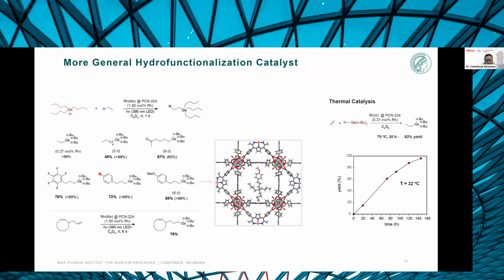What was interesting here is that we saw a real step function in terms of the decrease of the reaction efficiency as the size of the molecule increases. So for these fluorinated arenes, the reaction was complete after 1 day, whereas here, with the addition of the O-methyl substituent, the reaction time increased to 6 days, right about at the time where the product of the reaction becomes large enough that it just about can still escape from the pores.